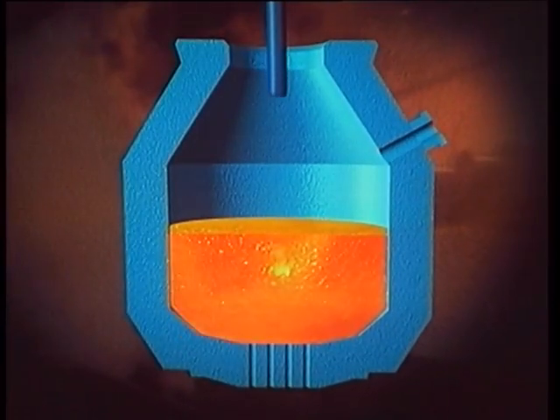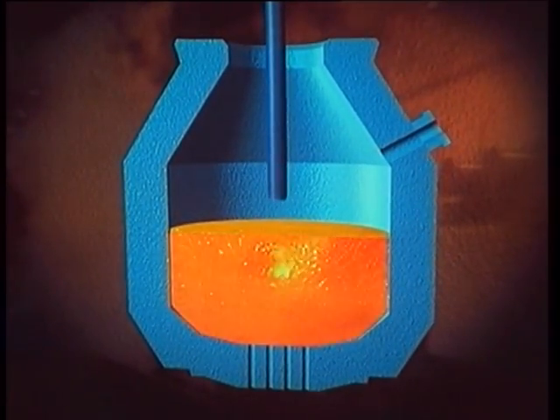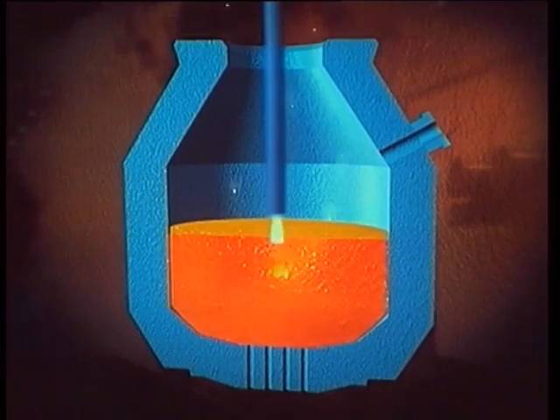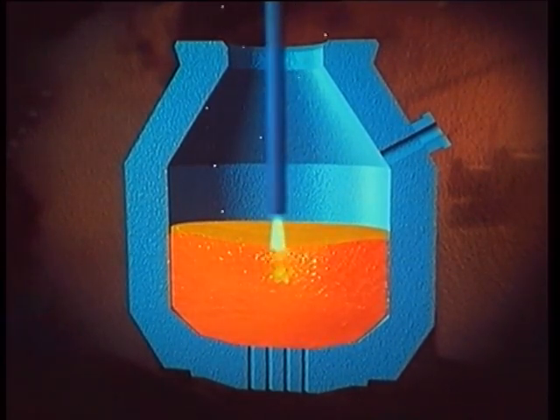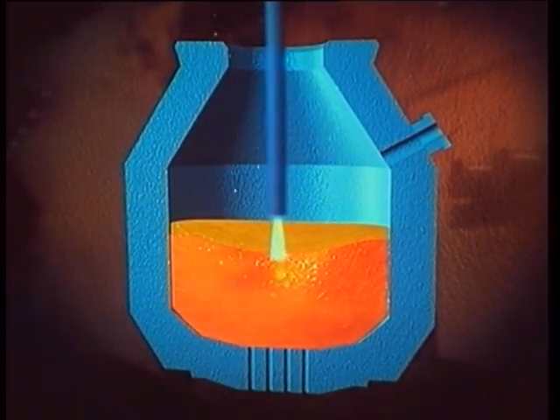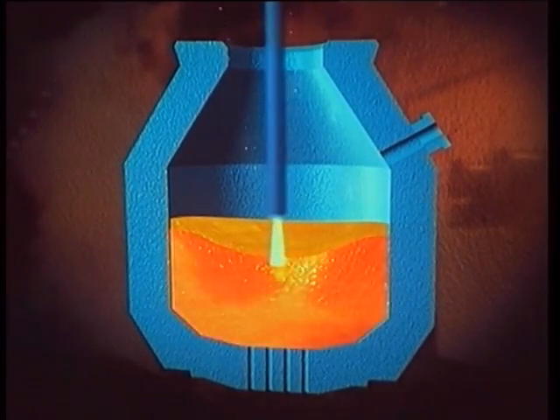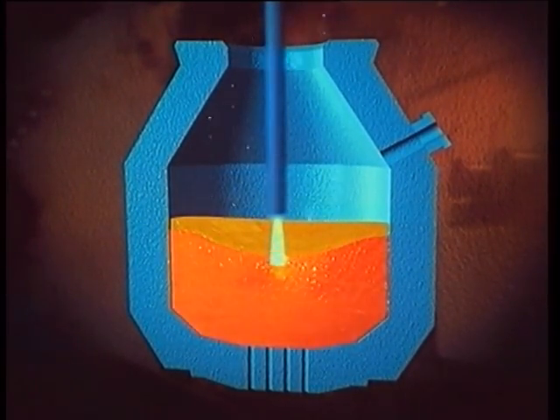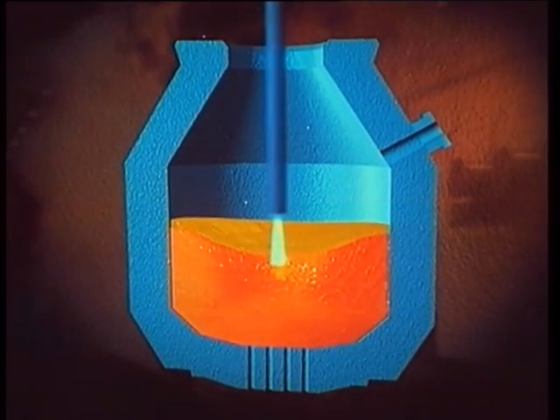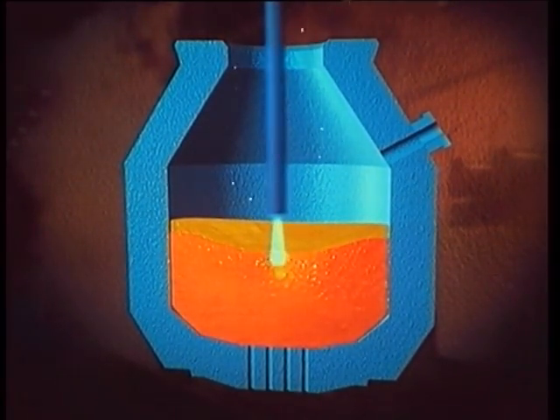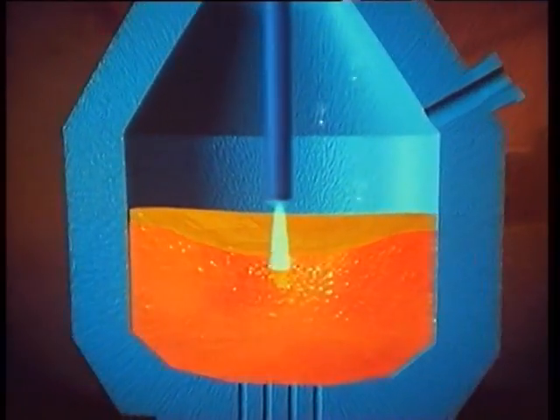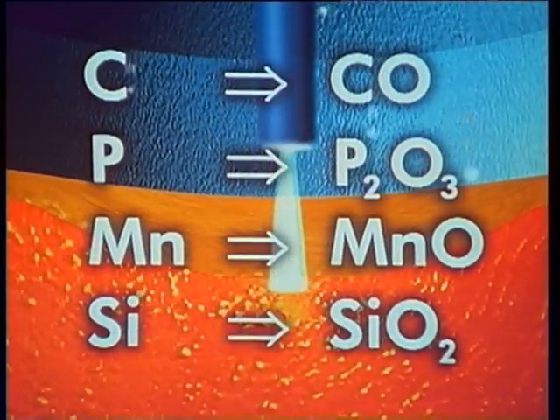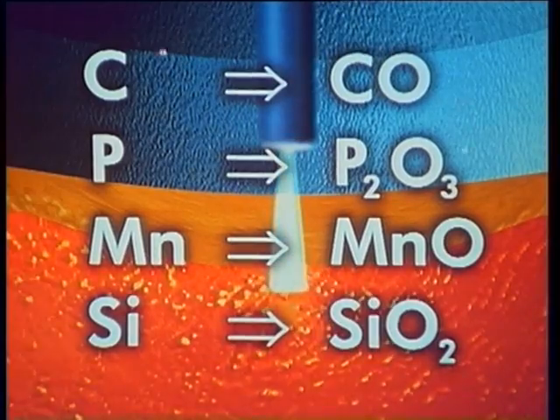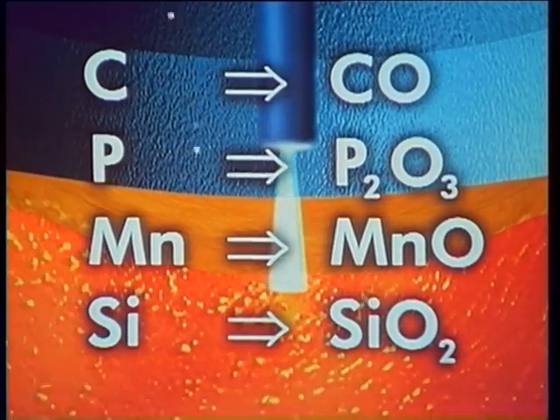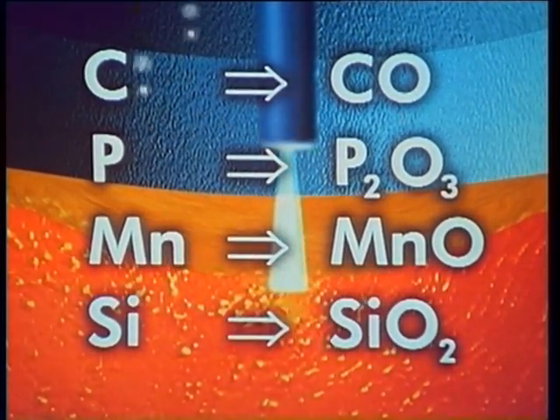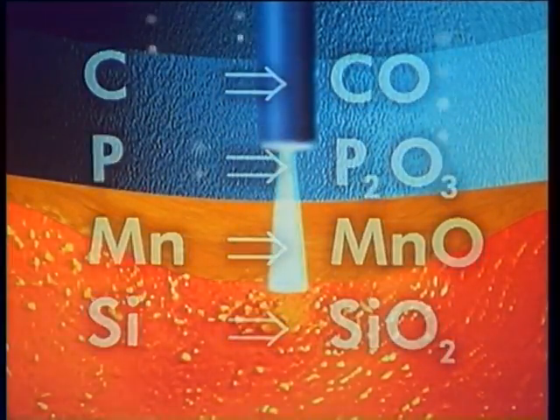After charging, the converter is turned upright. A water-cooled lance is lowered into it. Thousands of cubic meters of oxygen are blown into the charge with supersonic speed. The carbon within the iron oxidizes into carbon monoxide and heats the iron to white heat. This also oxidizes impurities such as phosphorus, manganese, and silicon. Their oxides are bound to the slag. Any iron oxide formed during this process is immediately reduced by special additives.